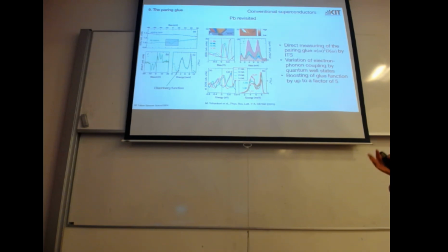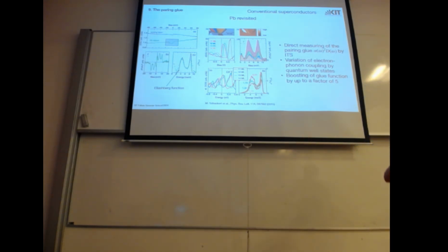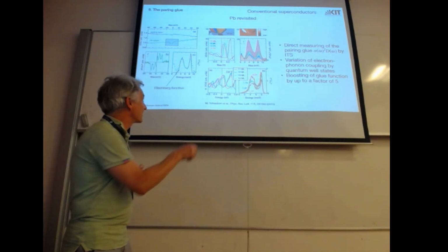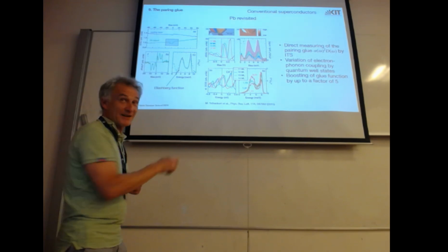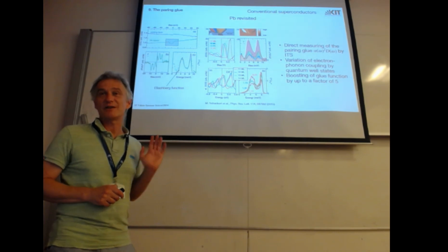If you are in between two quantum well states and you distort the lattice, hardly anything happens to the density of states. It is principally zero in the extreme case. And if you are at the border of a quantum well state and you change the lattice parameter, the dispersion changes, and the quantum well state will shift back and forth across the Fermi energy, which means you scatter a lot of electrons. This was our argument. This is naive experimental thinking, and you get something similar in DFT.